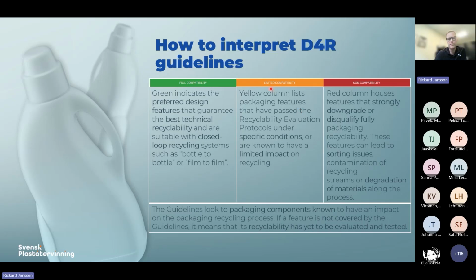And then you have these materials in the yellow column called limited compatibility, meaning that if you use these materials, for example, in a barrier layer, they will not hinder the packaging from getting recycled, but they can potentially lower the quality of the recycled material or lower the yield of the recycling process. And you typically also need to stay within specific conditions. So for example, you shouldn't use more than a certain percentage of this material, because then the packaging will be considered non-compatible with recycling. These specific conditions are mentioned in these rows for specific materials.